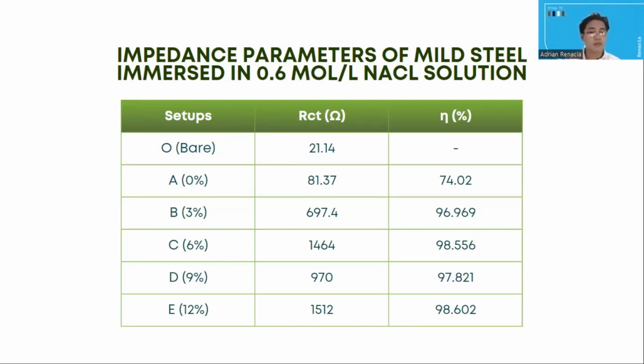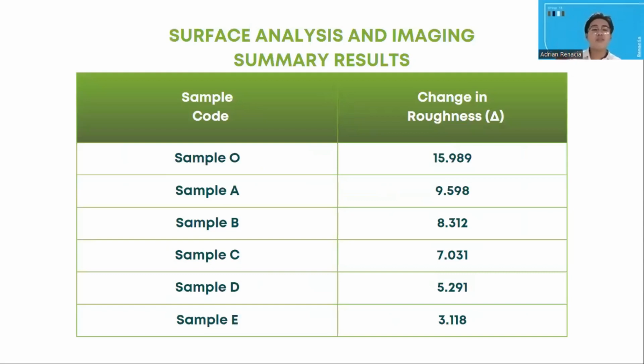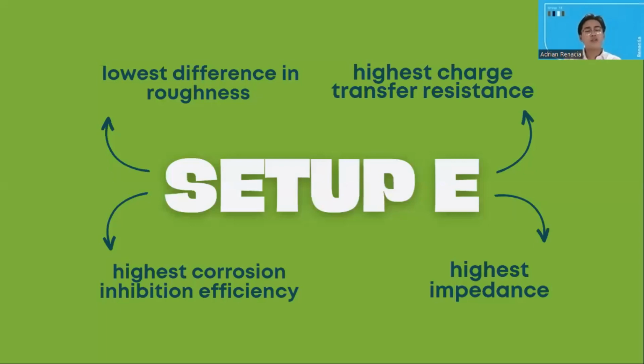of the inhibitor. While based on AFM analysis, the surface of the coating with the optimal concentration of LL extract shows a smoother surface with few crystal-like structures or difference in roughness average between pre-test and post-test of EIS, indicating an increase in its capabilities as a corrosion inhibitor when compared to the same coating without the presence of the extract. Together, the results show that the LL extract has really the potential to be an effective corrosion inhibitor for mild steel in chloride-rich conditions, opening up possibilities for its practical use in methods for corrosion protection and prevention.